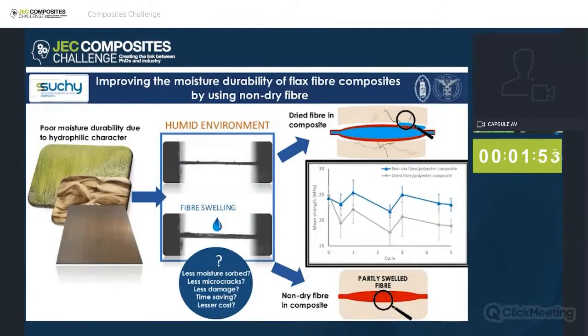So to test our hypothesis, in our study, we used accelerated aging for moisture durability evaluation, which is the wet-dry cycling. So we try to simulate both the hot-wet and the hot-dry weather conditions for both the indoor and outdoor applications of the composite. So the artificial aging that we use consists of 5 cycles divided into wet and dry conditions. In the wet condition, we use a relative humidity of around 89%, and in the dry condition, a relative humidity of around 32%. And then we also tested the composites at different cycles to measure the progression of damage throughout the cycle.